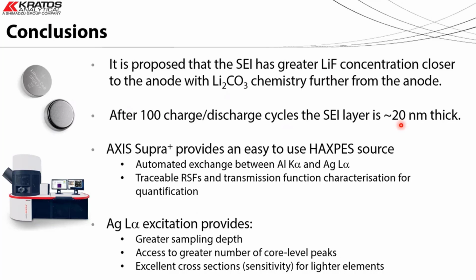I think, as Stuart pointed out, that from an instrumental point of view, the HAXPES is relatively easy to use. The change between the two sources is all automated through the software. We are now able to quantify the results because we've got the traceable RSFs, and we're taking care of the transmission function. And using the HAXPES gives us a greater sampling depth, as Sarah pointed out, access to a greater number of core levels and good cross-section sensitivity, even for lighter elements, particularly if you compare it to the higher energy photon sources.